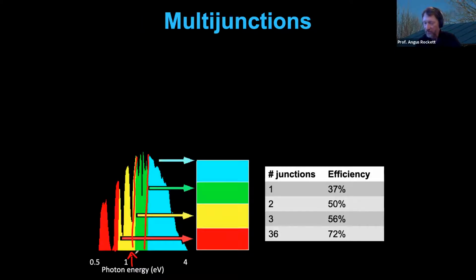So what we're going to do is we're going to stack solar cells on top of each other. We're going to have one solar cell that catches the blue light, maybe another one. If we had a 4-junction cell, one would catch the green light, one would catch the yellow, and one would catch the red light. So the theoretical limit to efficiency, if you had an ideal band gap around 1.4 electron volts, you could get to 37% efficiency.